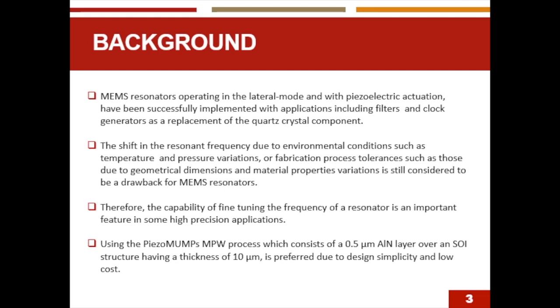Therefore, the capability of fine tuning the frequency of a resonator is an important feature in some high precision applications. Using the PiezoMUMPS process which consists of a 0.5 micrometer aluminum nitride layer over an SOI structure having a thickness of 10 micrometers is preferred due to design simplicity and low cost.